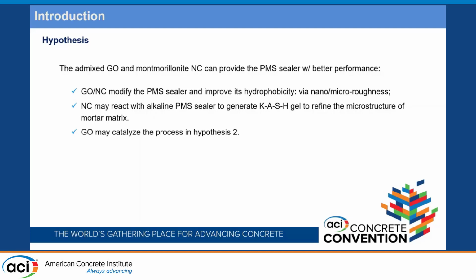The second hypothesis is that this PMS sealer is alkaline. So for the pozzolanic reactive nanoclay, we assume it will react with this alkaline PMS sealer and then generate more and more hydration products and then block pores. The third hypothesis is that graphene oxide is a fantastic nanomaterial. It can greatly improve the performance of cementitious materials. So here we assume it will catalyze the hydration process in hypothesis 2.